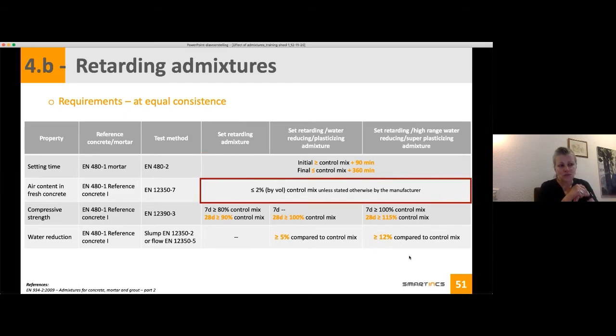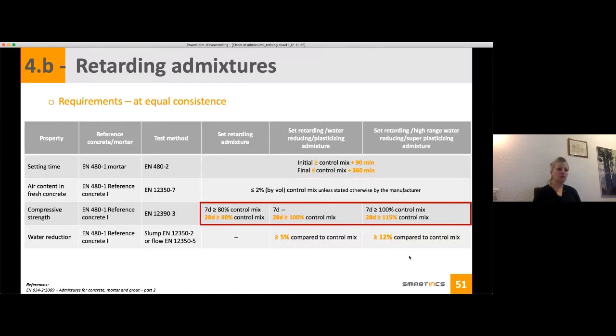What applies also to the three categories is the air content in fresh concrete, and the same as a dispersing admixture, it should not be more than 2% compared to the control mix. Now you have a difference in the requirements when it deals with the compressive strength. If you have a set retarding admixture as a standalone, at 7 days your compressive strength should be 80% of your control mix, and at 28 days, 90% of your control mix. So between 7 and 28 days, you should also have an increase in strength.